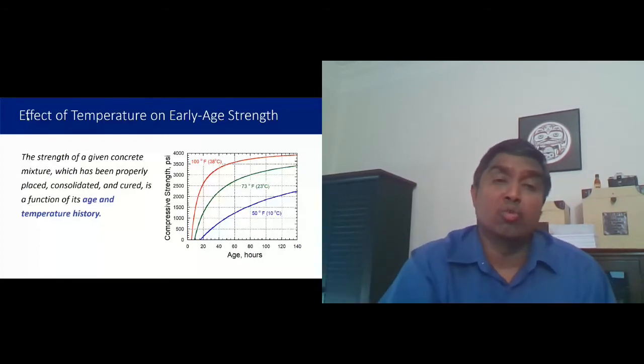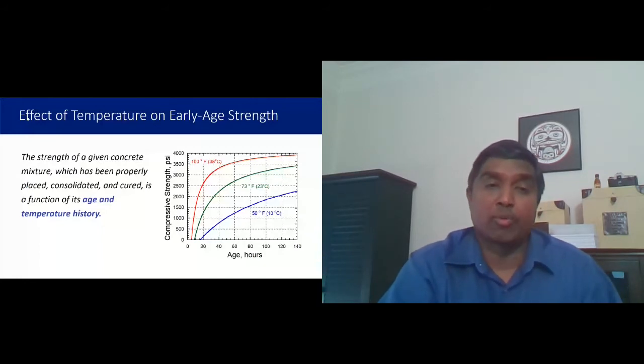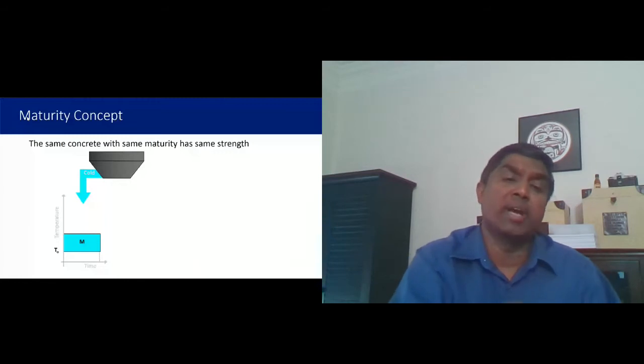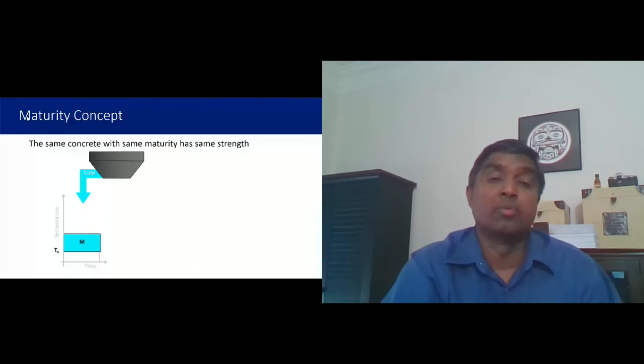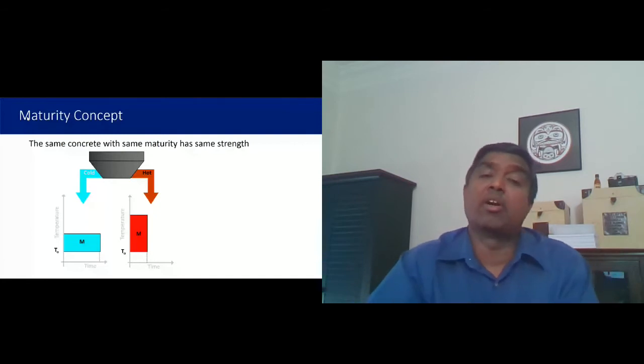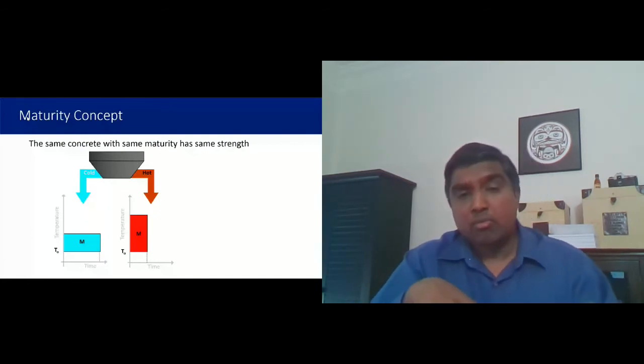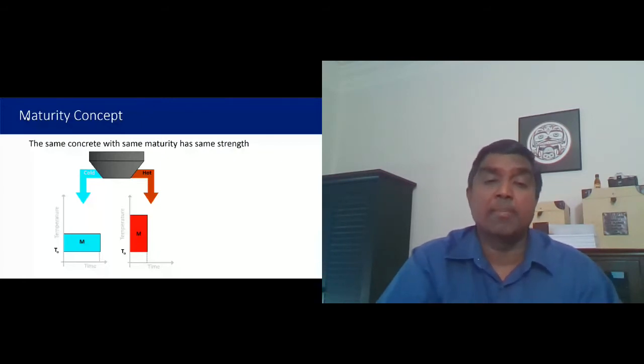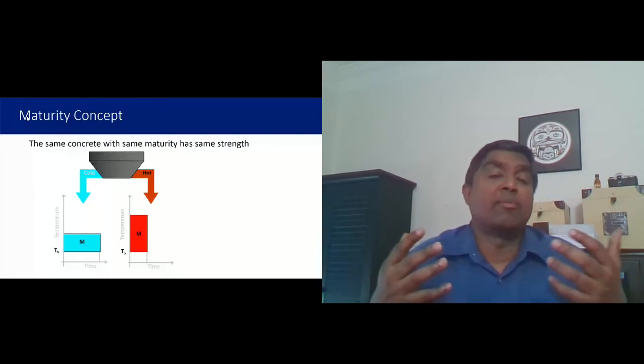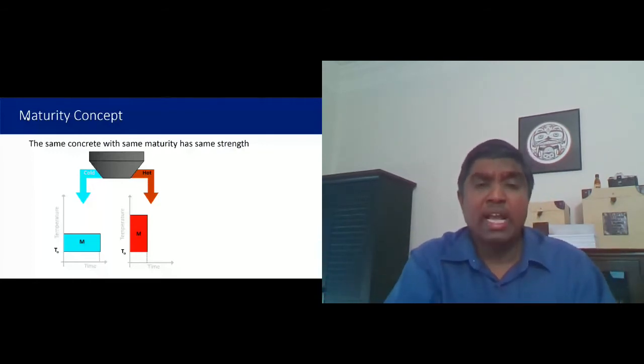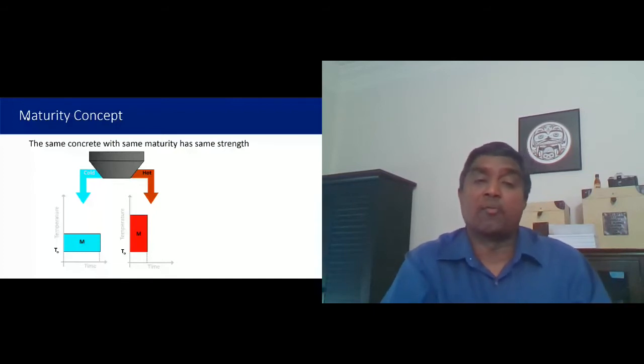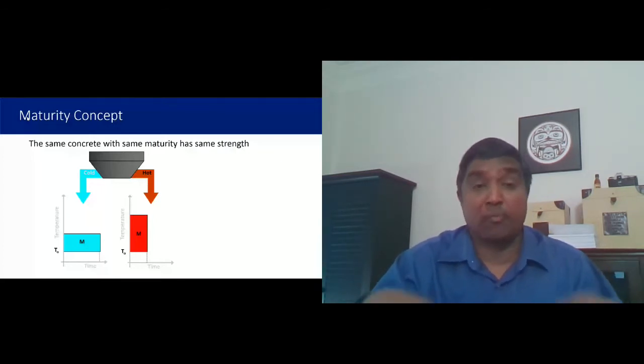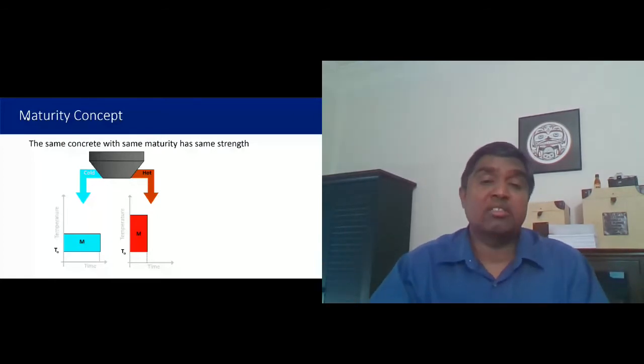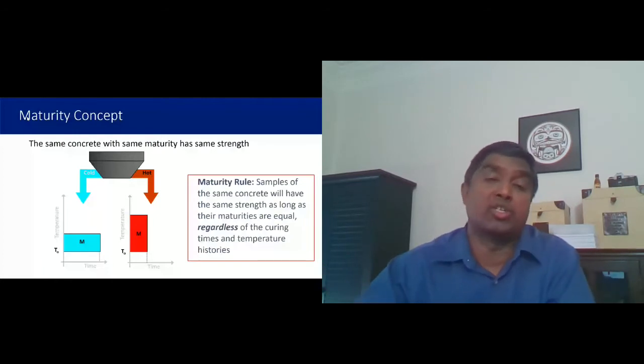Basically it sees how both of these impact strength gain, and that's all it really is. So let's assume that we have concrete that's exposed to cold weather, and all we're really doing is measuring time and temperature, and similarly we also have concrete that's exposed to hot weather. Again, we are also measuring time and temperature. So when we measure the area under the time-temperature curve, let's say that area, we give it a name called M, which stands for maturity. As long as the area under the curve of time and temperature is the same for these two concretes that are exposed to two different weather conditions, for the same concrete mixture, their strengths should also be the same. That's really what maturity is all about.